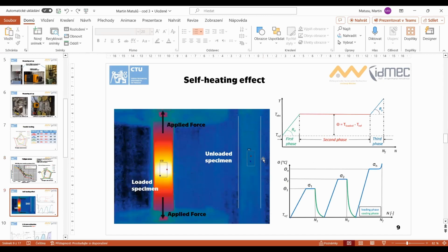So let's go to the key point of this presentation, the self-heating effect. The self-heating effect comes naturally during the fatigue testing, dynamic loading. It comes in 3 phases. The first phase can be described by the initial incline. The second phase can be described with difference of temperature, and the third phase, which is basically the end of the testing, is when the crack initiation begins and leads to the fracture of the specimen.